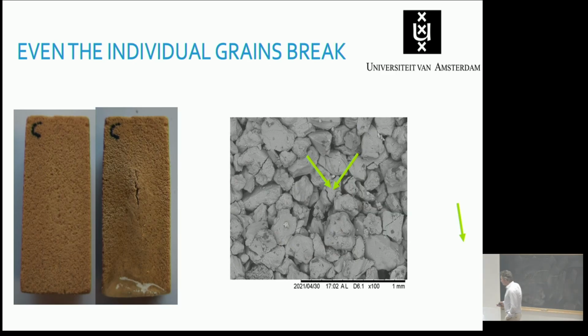And so if you zoom out, you can get this kind of damage, but if you zoom in, if you bring your material to the electron microscope, oh, the arrows actually got displaced. But you can see that even the individual grains can break in two. The pressure is so large that you can completely destroy the sandstone.